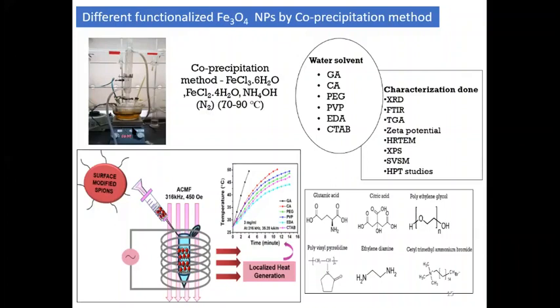We did it in a nitrogen atmosphere, and we coated with glutamic acid. Here is the structure of glutamic acid. There are hydroxyl groups over here and amine groups over here. Then there is citric acid; we have taken trisodium citrate, so three carboxyl groups are there, which can link with the iron ions in the nanomaterials either by electrostatic force, by covalent bonds, or by coordination bonds.